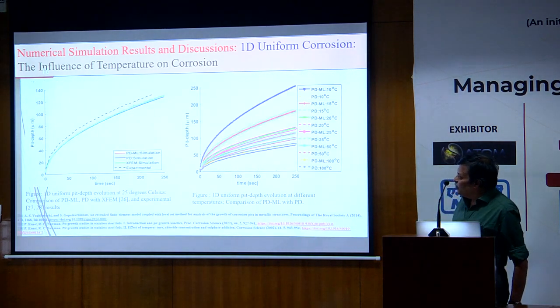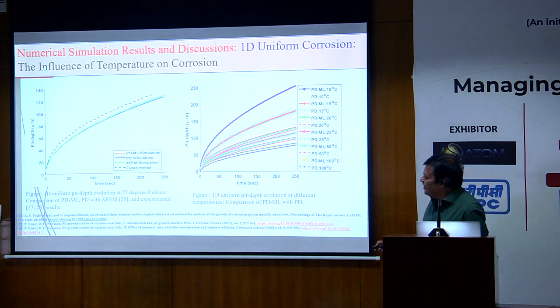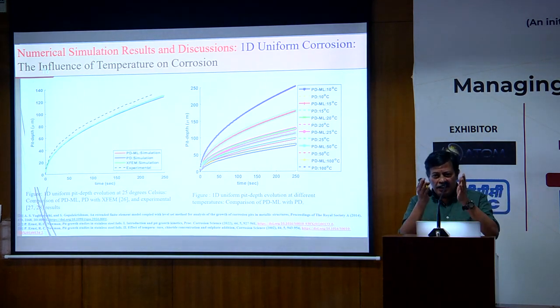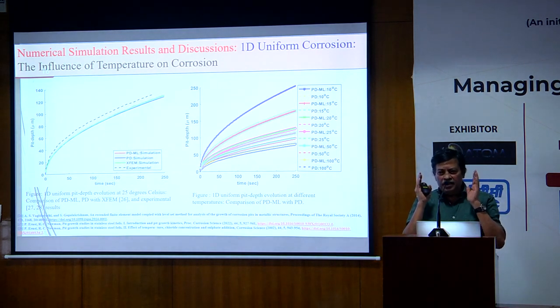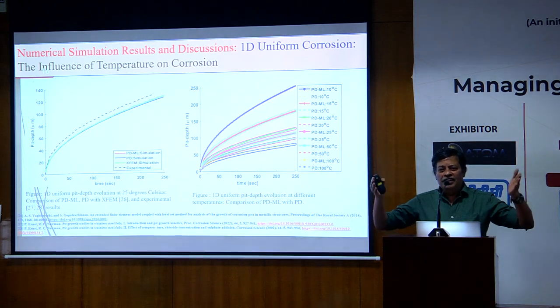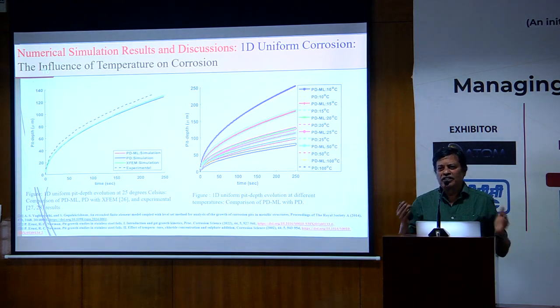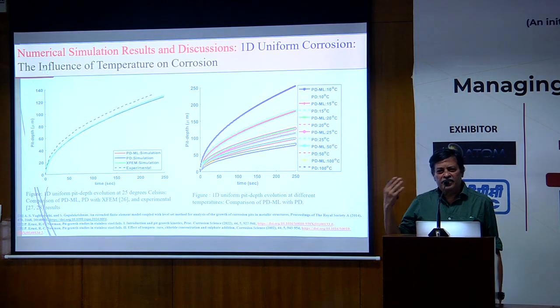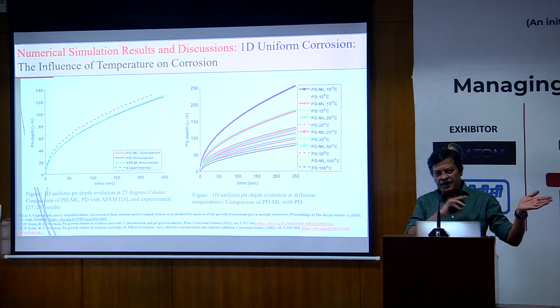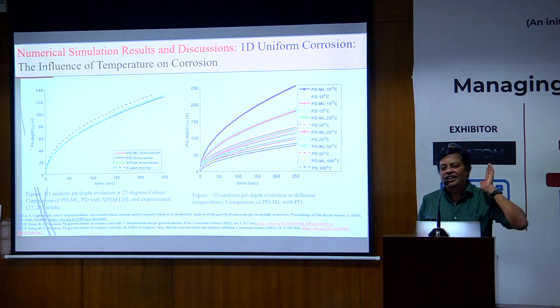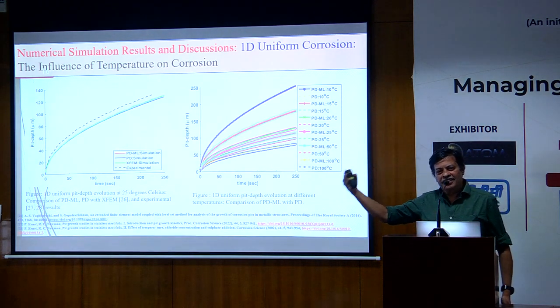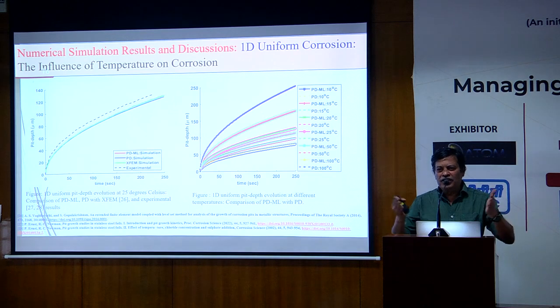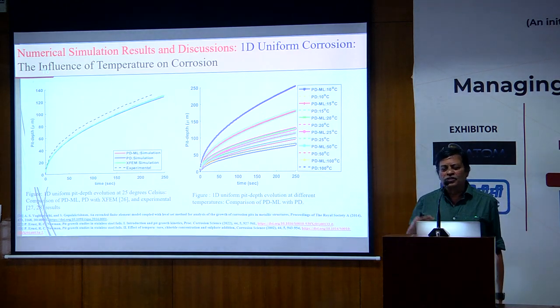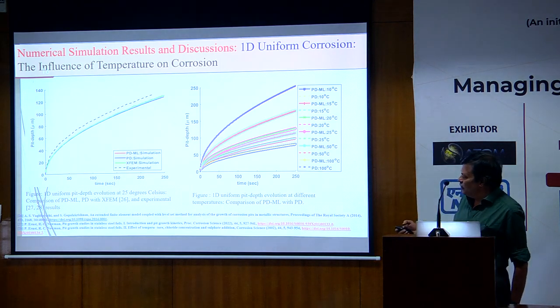So this is the pit profile, what we predicted. The idea here is, in the region very close to the pit, we use what is called the peridynamic solution. Far away, we use the ML solution and FE solution put together. The ML solution is basically obtained from FEM. We trained the whole network, and then we created an input-output map between corrosion concentration and the responses, so that we can put them together. By this approach, we reduced the computational cost by 5 times, and we were able to get a very good approximation to our experimental results.